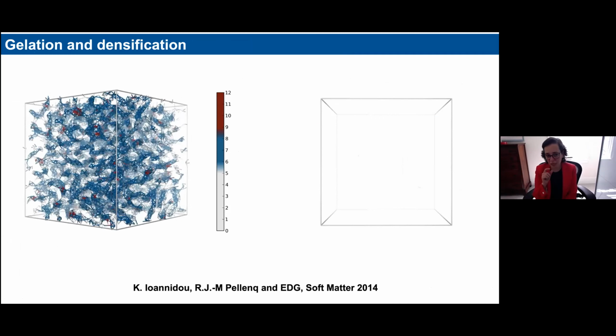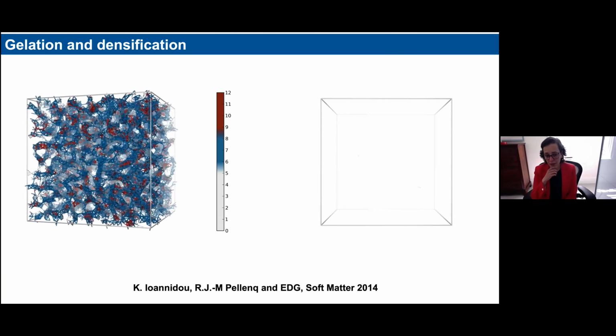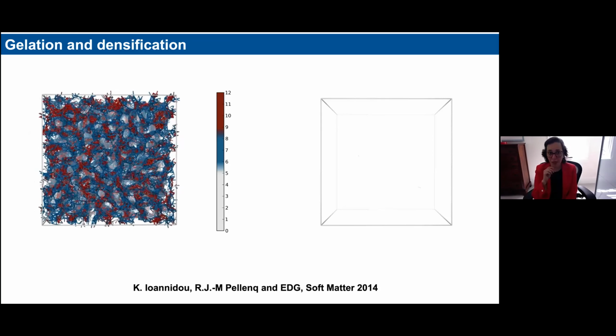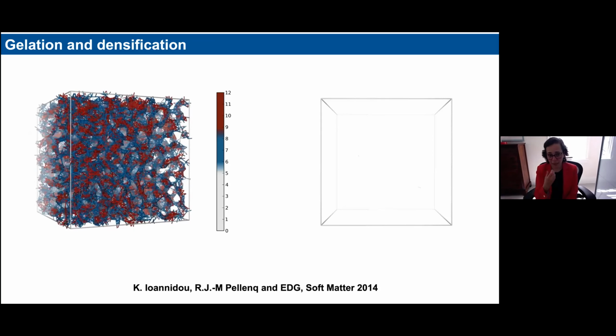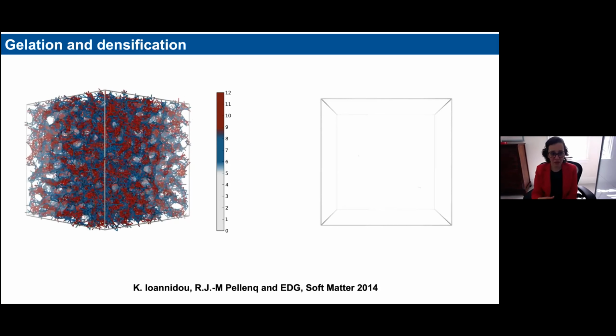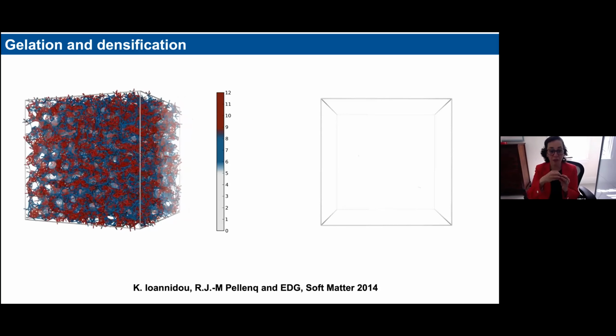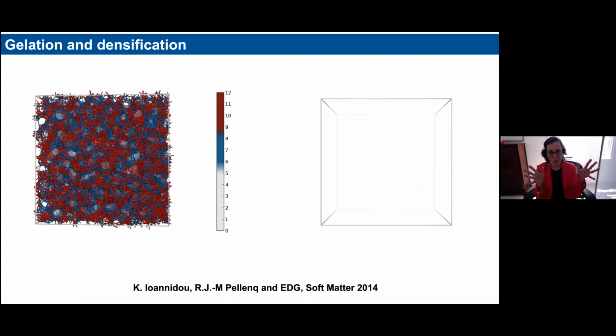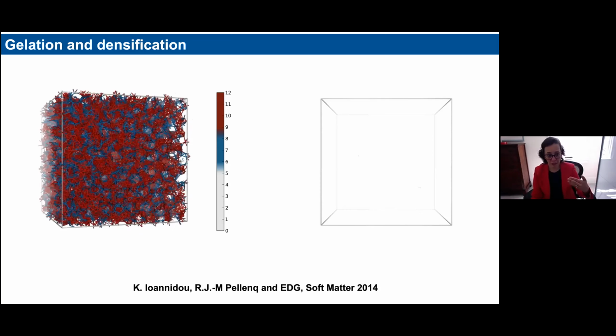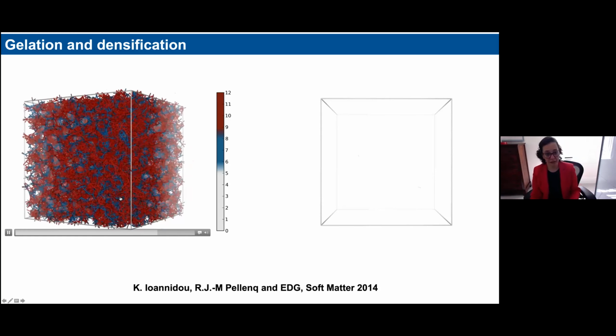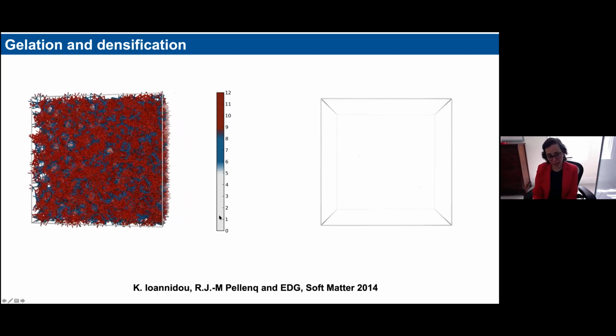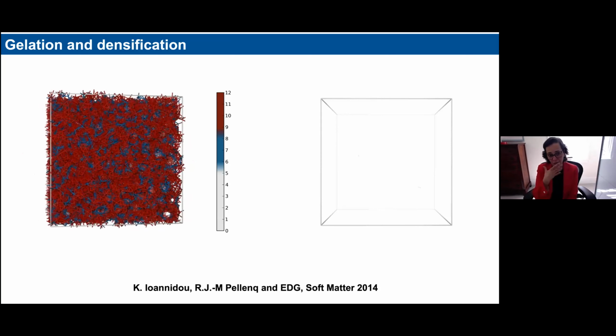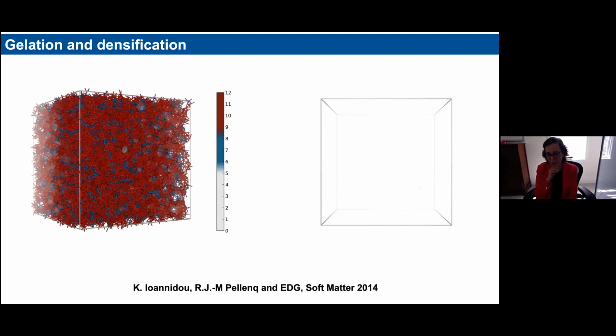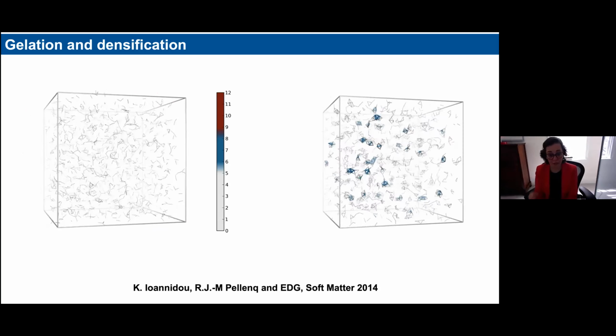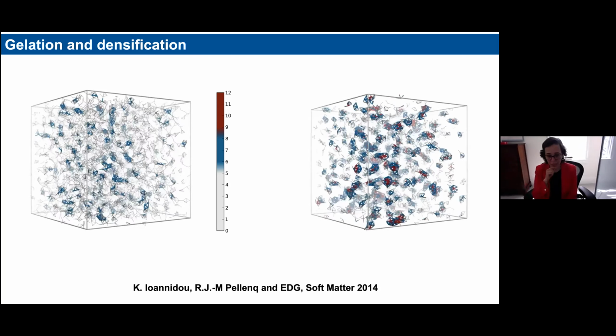What you're seeing is just the links between the nanoparticles, for clarity. The color represents the number of neighbors that each particle is bonded to. You can see that from the beginning you have formation of fibrils, which then branch and form a network. The network has a more homogeneous pore size and then continuously densifies. This corresponds to the aggregation and gelation process with interactions that are very typical of the early stages of hydration, which have this relatively high repulsive shoulder.